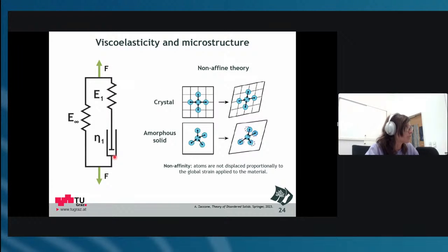The same thing comes up if you look at these viscose fibers and also the lyocell fiber: they have a certain degree of amorphous, disordered structure in themselves, especially the viscose fibers, I would say. Actually, a reviewer of my paper came up with this comment, so I really liked it. This was very, very constructive, and I did not know about it at all. There is this non-affine theory for disordered solids. When you deform a crystal, the atoms in the material will always be displaced proportional to the global strain that is applied. But in an amorphous solid, as you can see down here, this is not so much the case. If you deform the material, these dashed lines are where the atoms actually should be, but they relax to other positions, and that is called non-affine displacement.